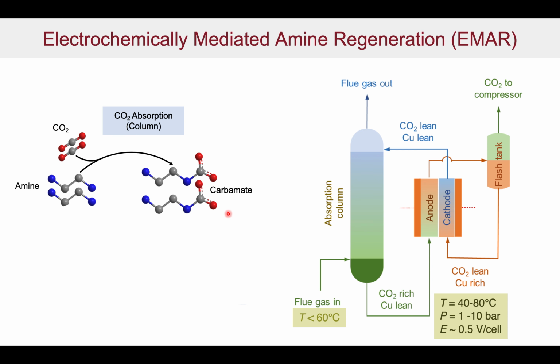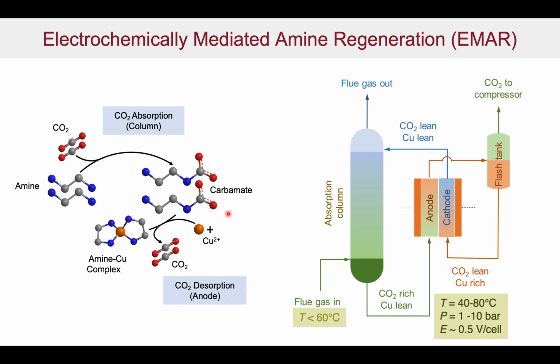But rather than doing this thermally by heating up, we take it into the anode chamber of the system, where we now add copper ions through oxidation, and this will then complex with the amine and kick off the CO2. Once you've got that, we can then disengage the CO2 in the flash tank, and then the solution can be fed back to the cathode, as an amine copper complex. In the cathode chamber, we reduce the copper, and we then regenerate our amines, and the copper is plated out on the cathode electrode, and we can go through this complete cycle.